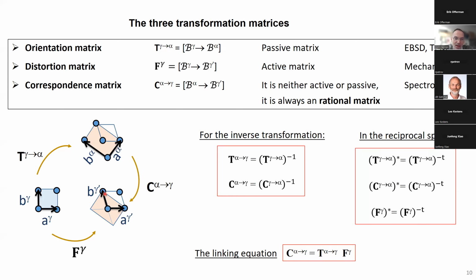But these distorted vectors here, b gamma prime, correspond to specific vectors in my daughter phase. For example, b gamma prime here is 1/2 of a alpha plus 1/2 of b alpha. Here it's 1/2, 1/2. And a gamma prime is 1/2, minus 1/2. So I can encode this specific link between a gamma prime and b gamma prime with a alpha and b alpha by what is called, not by me, in general, the correspondence matrix.